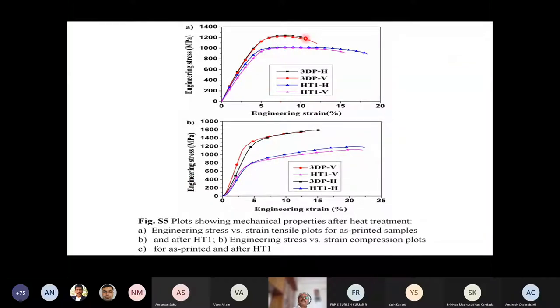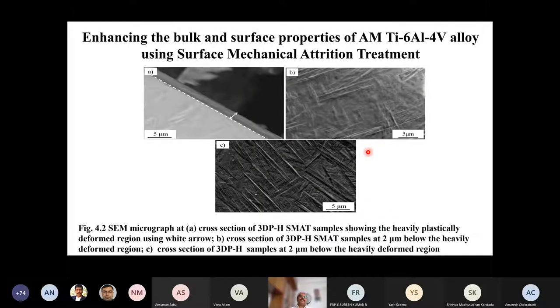Here, the stress strain curve is shown. We could see that the heat treated ones are the triangular ones. So they have shown larger ductility. And of course, there is some reduction in strength, but the ductility is significantly larger. And so particularly the toughness will be appreciably different in both cases. Therefore, sometimes we need more ductility, sometimes we need more strength, and accordingly, by heat treatment, we can tailor it.